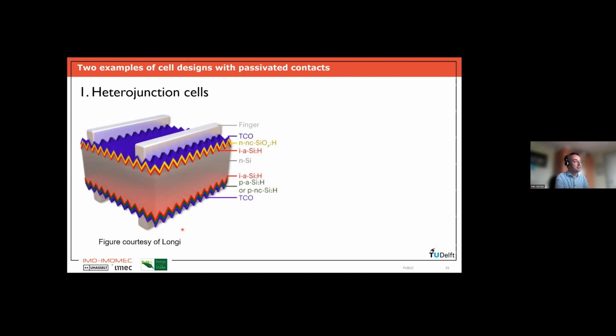So this is like a completely different cell concept than what we have seen before. So here you typically have an N-type silicon wafer. And the N-type silicon surfaces, both the front and the rear, are passivated by very thin intrinsic amorphous silicon layers. And then to form an emitter or a back surface field, very thin doped layers of either amorphous silicon or something else like nanocrystalline silicon oxide are used. And then we have on both sides a transparent conductive oxide for lateral transport. And then we have, of course, the metallization.